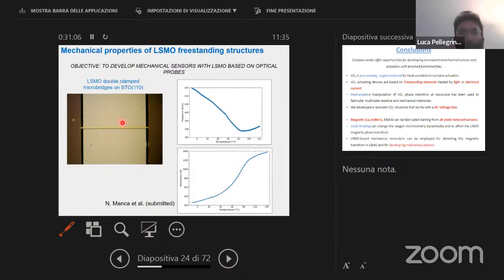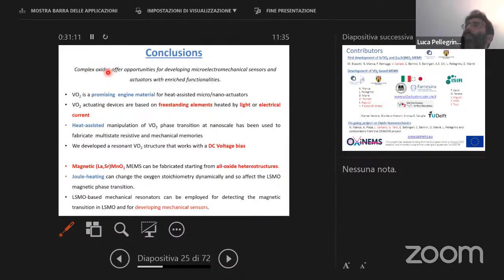So it's time to conclude. These are the conclusions. I showed you that complex oxides offer good opportunities for developing microelectromechanical sensors and actuators with enriched functionalities. I showed you two examples of two interesting materials. One is vanadium dioxide, showing some memory effect and use in actuators, and also a magnetic manganite, showing that we can use these compounds even for experiments with the micro hot plate, changing the oxygen stoichiometry and studying the effect of the change of the oxygen stoichiometry on the physical properties. And I also showed you a preview of using this manganite freestanding structure as mechanical resonators.